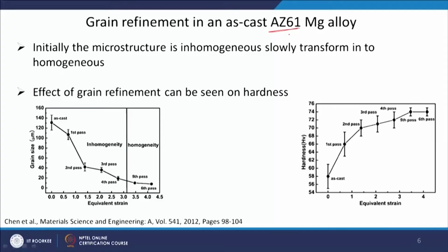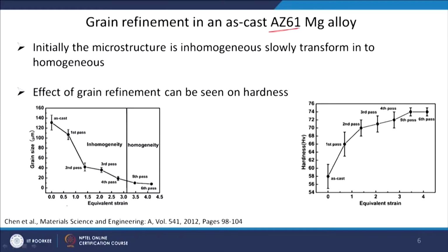This is an example of grain refinement in as-cast AZ61 magnesium alloy. So, this is another good example that you can convert an as-cast material into a wrought material, with a very refined or very fine microstructure. As you know, magnesium alloys are HCP materials, so deformation is usually very difficult. So, in this case, because you are able to introduce a lot of deformation through continuous change of the direction of deformation, you are able to introduce a lot of strain in the material. So, strain you can see on the x axis here. They are able to achieve a strain of 4 after around 6 pass or so.